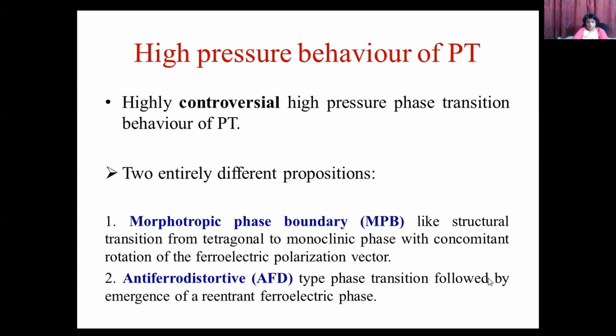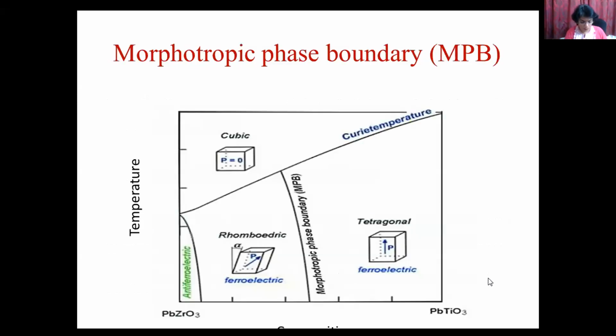Now, talking about recent studies, the high pressure behavior of lead titanate is highly controversial because there are two different propositions which are entirely different. The first picture says that with increasing pressure, there happens a morphotropic phase boundary, commonly known as MPB, like a phase transition from tetragonal to monoclinic phase, associated with a rotation of the ferroelectric polarization vector. The second picture says that there is no such thing as polarization rotation. Rather, with increasing pressure, we get an AFD type phase transition, in which after a critical pressure, we get a reentrant ferroelectric phase.